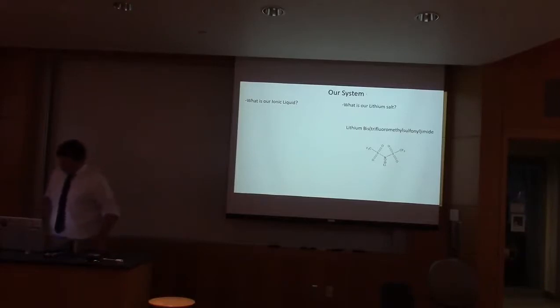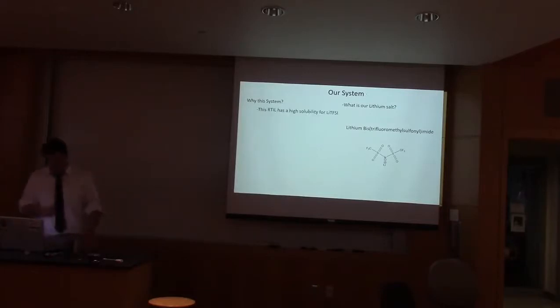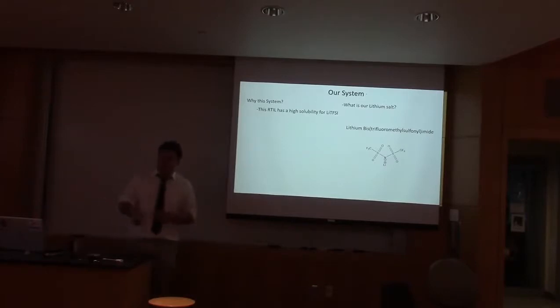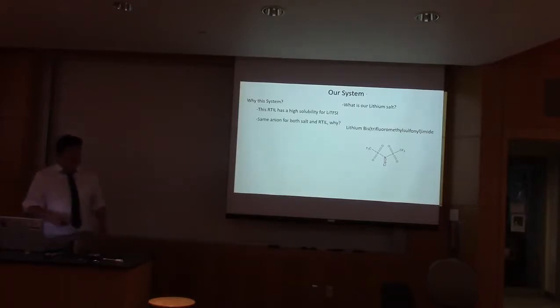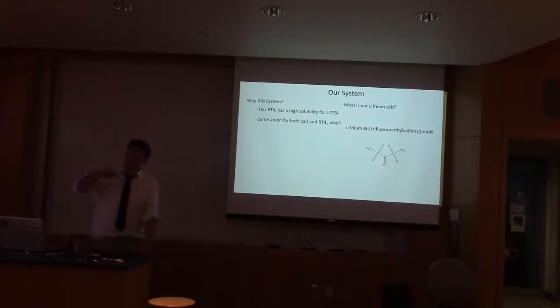We chose our lithium salt to be lithium bis-trifluoromethanesulfonimide, or lithium TFSI, to dope into our room temperature ionic liquid. In particular, we chose this system because the pyrrolidinium-based cation had a very high solubility for lithium TFSI. We also chose to use the same anion for both the salt and the room temperature ionic liquid in order to specifically study how the lithium ion affected our conductivity and viscosity. We eliminate variables by using the same anion in both.